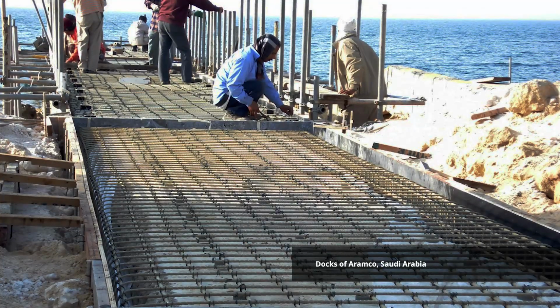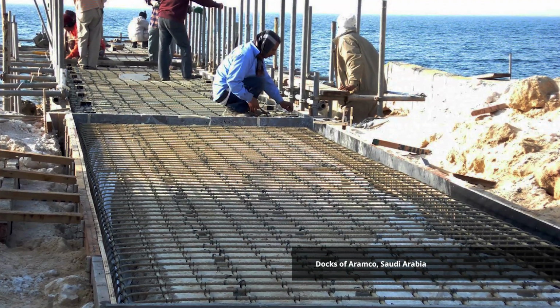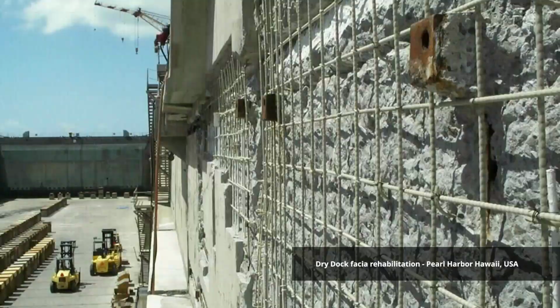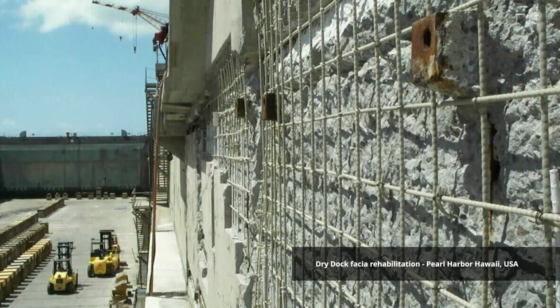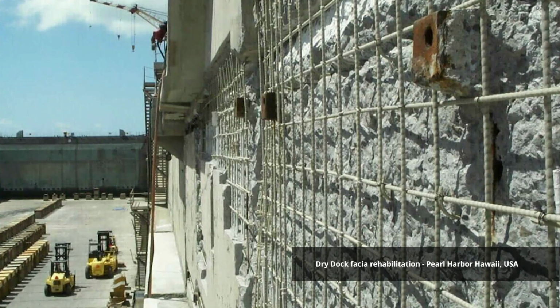So whether the structure is fully in GFRP or GFRP is only used on the outside, it's the best way to remove corrosion, but also limits the risk of getting cracks. And so that's really the main feature. Corrosion doesn't exist with GFRP, and therefore we can place them very close to the surface. And in some cases, we can even reduce the volume of concrete by reducing the concrete cover.